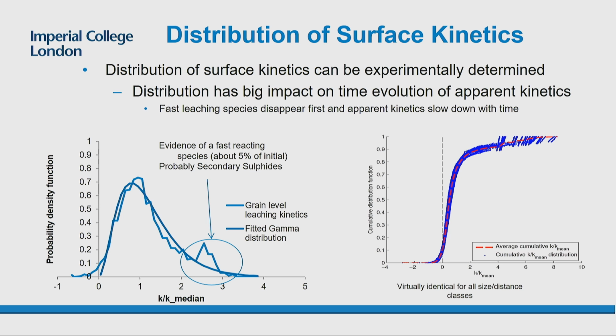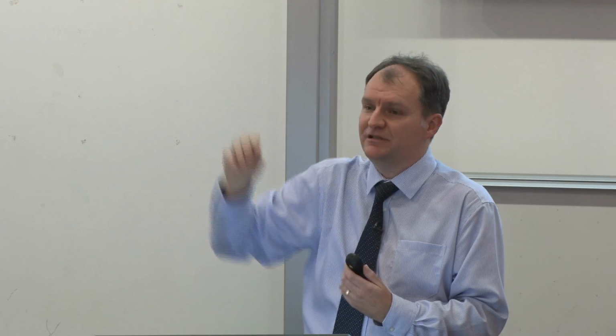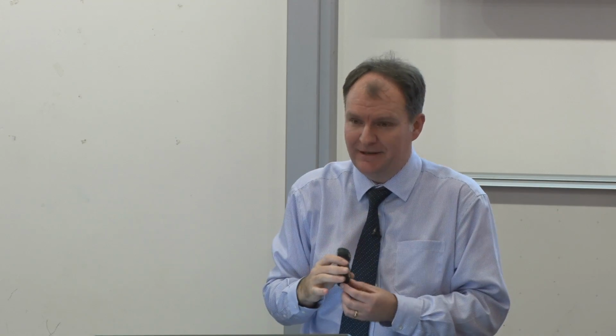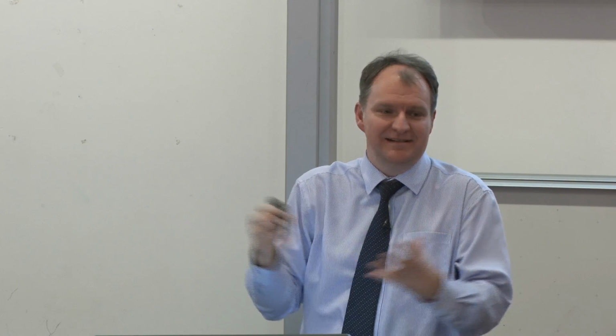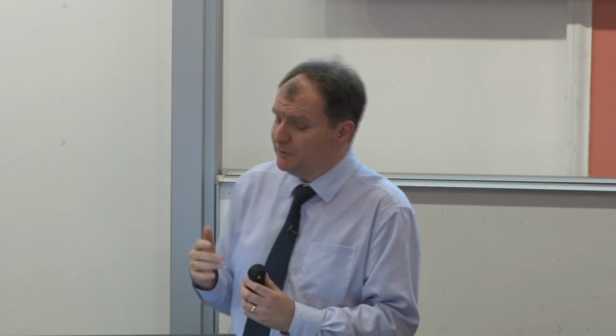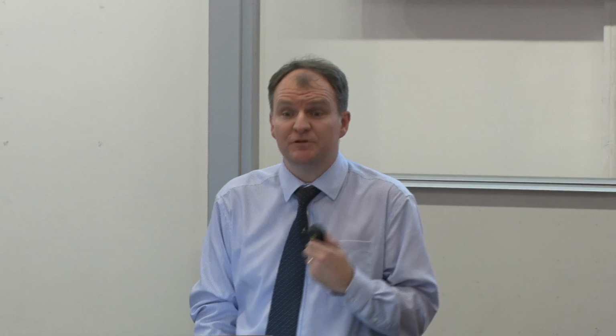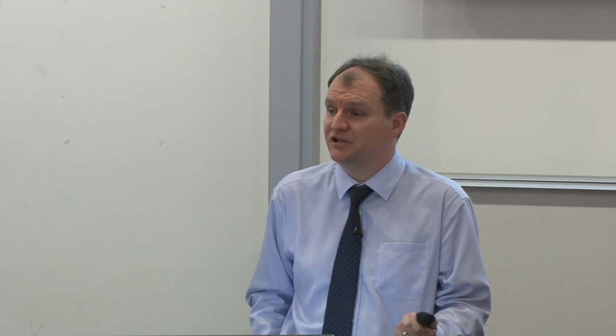So this is the leaching rate divided by the average for that category. And strange enough, it falls into one relationship over pretty much all the systems, all the categories we measured, which was actually surprising. We'd expect some grain size effect to the relative leach rates. But once we did this, we can get this shape, and this was really important for subsequent simulations because the